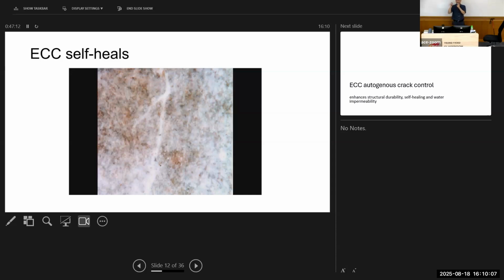And the crystals, the growth of those repair materials, they often start on the fiber surfaces. So they start growing around the trunks, and then they connect themselves together. And then they fill the whole crack. It's absolutely amazing. Okay. And I think that in a big way helps the integrity of this repair. You can actually make concrete do this kind of self-repair as long as you crack the concrete back and then expose it to favorable conditions, especially modern day high-strength concrete when you have a lot of unhydrated cement grains. You can do that, and they would reheal.